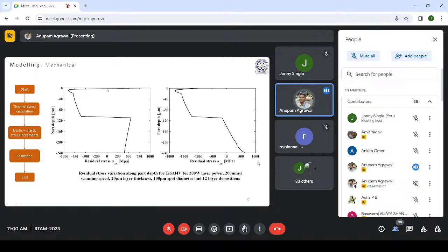Why is it unwanted? Because tensile residual stresses can lead to early fatigue failure. So for fatigue-critical applications, we need to make sure that tensile residual stresses are not there. Rather, compressive residual stresses are very good, because the fatigue life gets improved if compressive residual stresses are there in any part. Many times you might have seen that a typical post-processing for metal-based products is shot peening. Once the products are made, they are shot peened. However, the objective here is that we tune the laser or process parameters to get the minimum possible residual stress. This is the sigma xx component only. The sigma yy component also shows compressive residual stresses on the top surface.